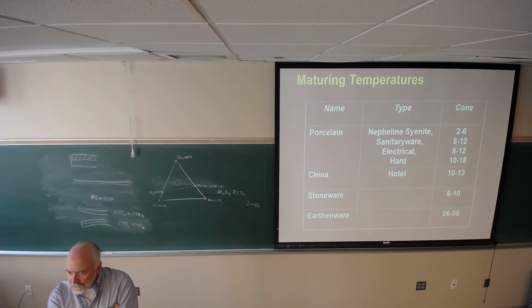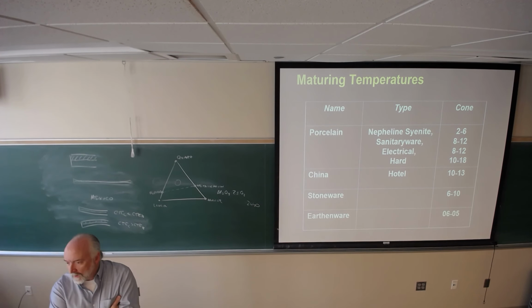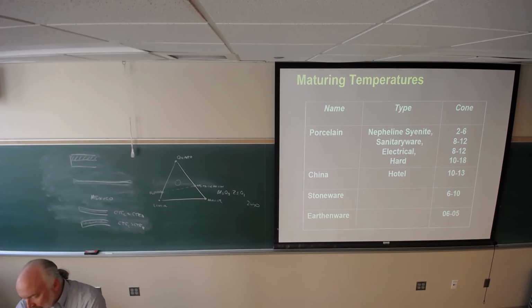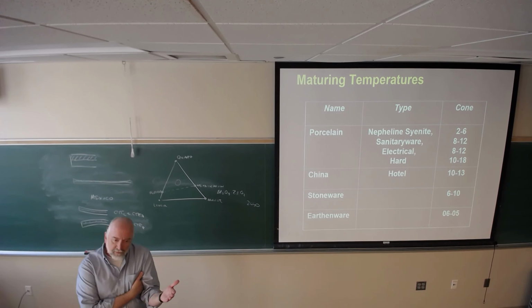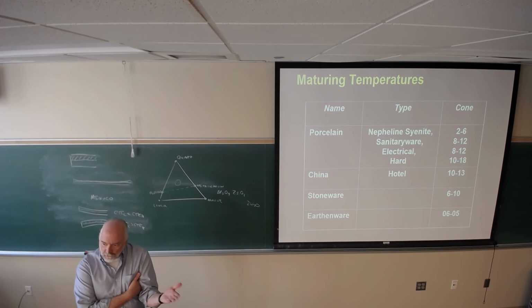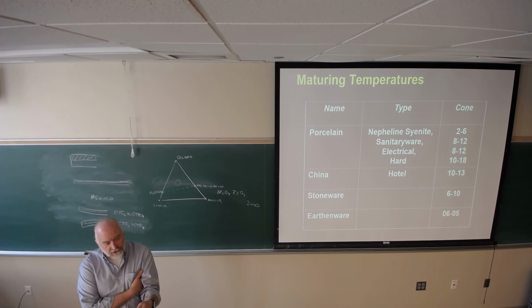The downside is there's no shrinkage to speak of in bisquing, right? Why is that a problem? Because then defects that you generate that haven't shown up yet will show up in the final firing when you take it up to peak temperature, right? So that means that you bisque low and glaze high, right? That argument was sort of a porcelain designation, but to bisque high to fully densify the body and then glaze and fire lower was designated China.